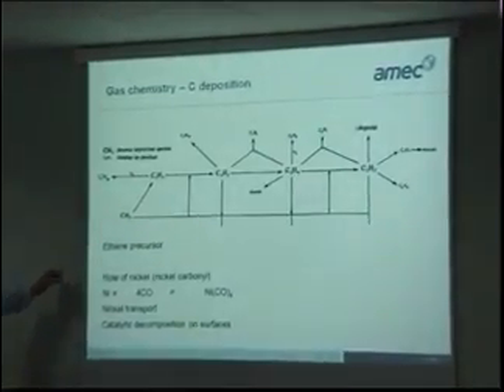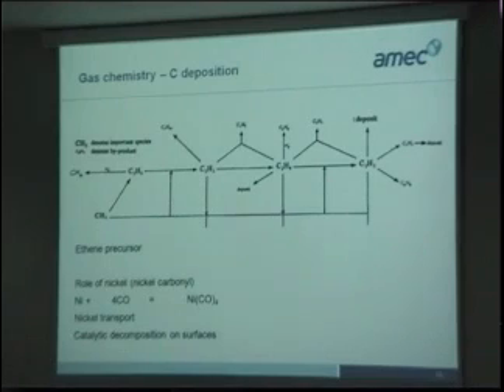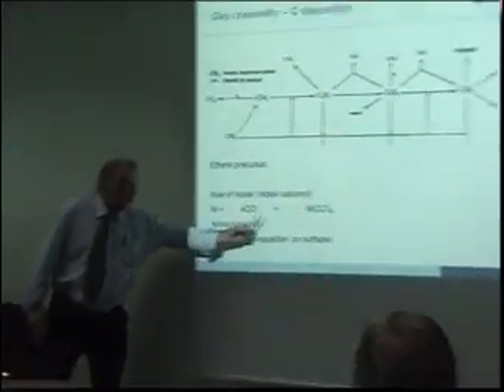I mentioned carbon deposition earlier, and the precursor for this is ethene. One of the mechanisms of carbon deposition is via nickel transport. In the reactor, you'll have several types of nickel alloy, and this will interact with the carbon monoxide to form nickel tetracarbonyl, and unfortunately nickel tetracarbonyl is volatile, so it gets into the gas phase, gets transported around the reactor, and in cooler parts it can deposit. Now the kinetics of this and the thermodynamics of this is such that increasing the temperature will increase the rate of formation of nickel carbonyl. But the thermodynamics in that sense is in your favour. An increase in temperature shifts the equilibrium the other way.